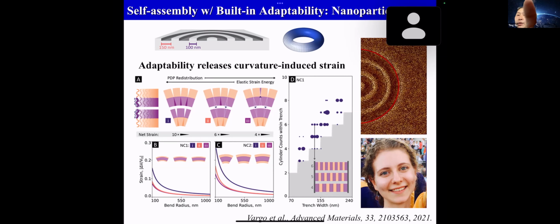And Emma did a very simple analysis, basically looking at the strain for bending cylinders or lamellae, and how you're going to deal with this interface mismatch between the inner side of the ring and the outer side of the ring. And as you change the distance away from the center, you also change the curvature. So this is where the adaptability of the system comes in very handy. Imagine if the system is able to regulate which individual component fills the gap or takes material away, you're going to release the elastic constraint from the bending of the microdomain.